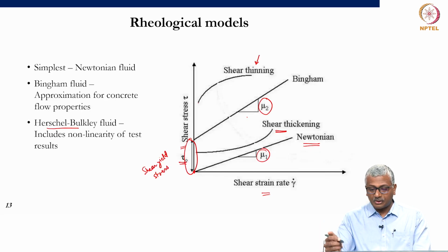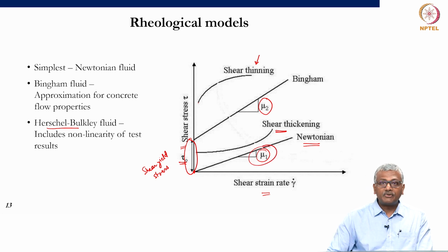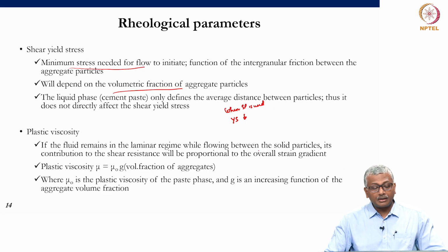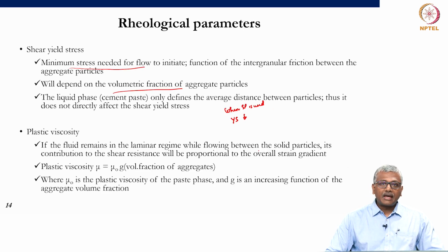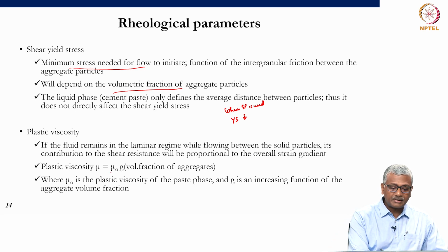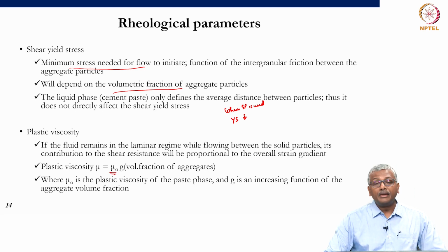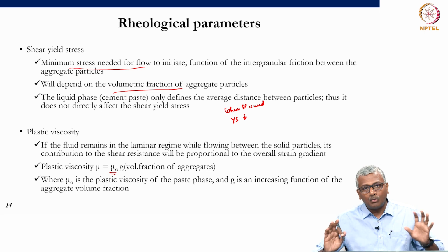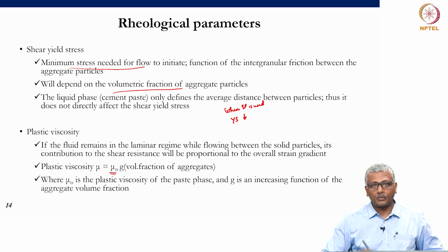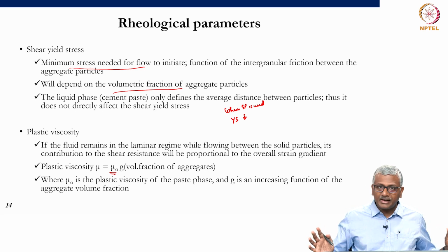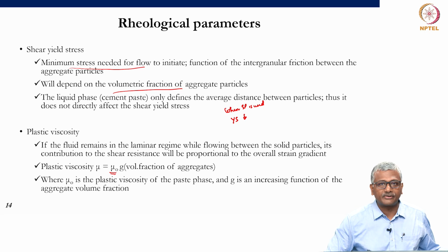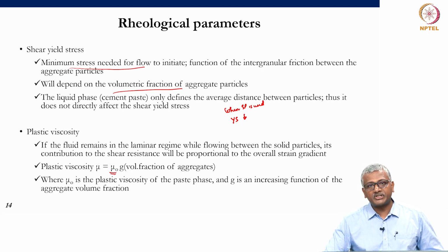So, that is why we get this sort of a relationship here, that viscosity is more or less constant for a laminar flow. Now, the plastic viscosity of the concrete can be defined as the plastic viscosity of paste, mu naught, multiplied by some sort of a function of the volume fraction of the aggregate particles. Okay. The more the aggregate, again the more difficult for the paste to carry this aggregate along with it. So, here if the paste is less viscous, it still has to carry a lot of aggregate with it. So, the overall concrete viscosity will then suffer if you have too much aggregate in the system.